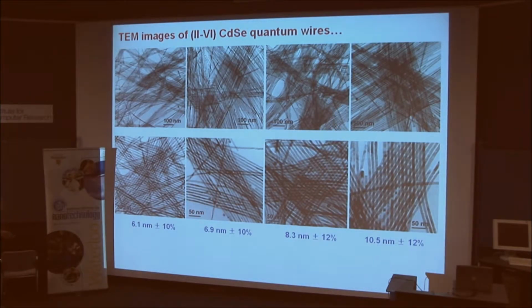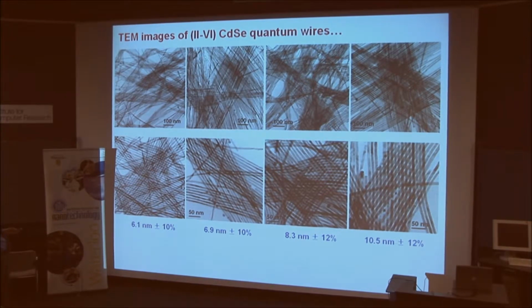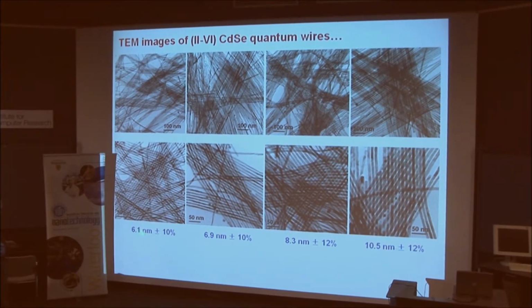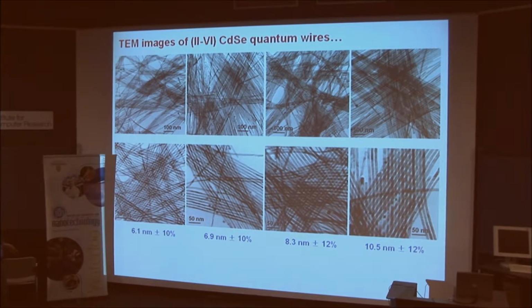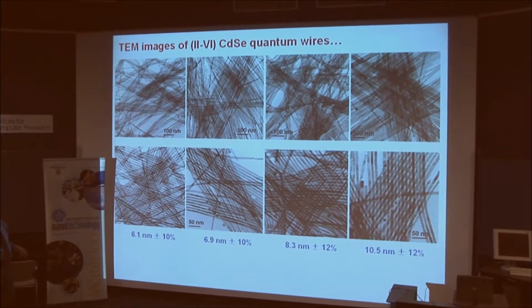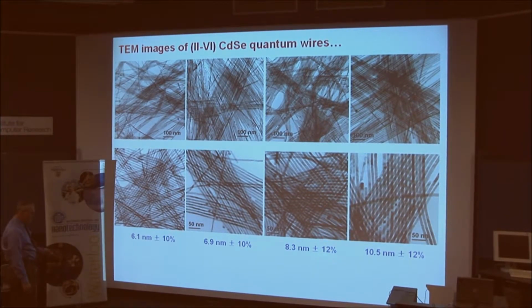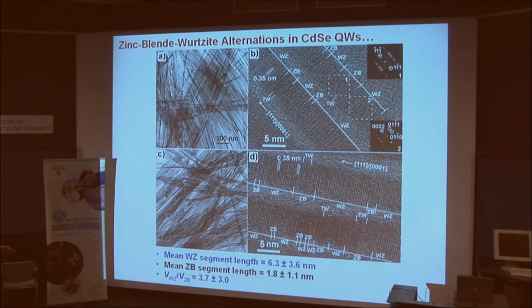So here are some examples of cadmium selenide quantum wires having different diameters, which we've purposely grown over that diameter range. And you can see that they are straight and, let's see, roughly all the same diameter. In other words, your eye tells you at least that the diameter distributions are reasonably narrow, and here are the distributions expressed as a percentage of the mean diameter. This is one standard deviation in the diameter distribution expressed as a percentage. They're also essentially or almost single crystalline in character.